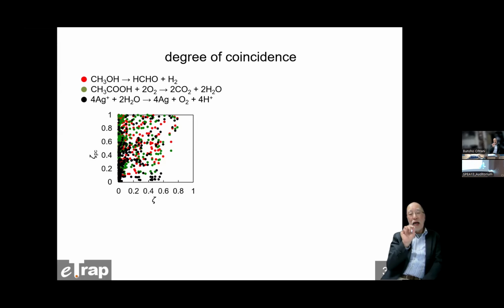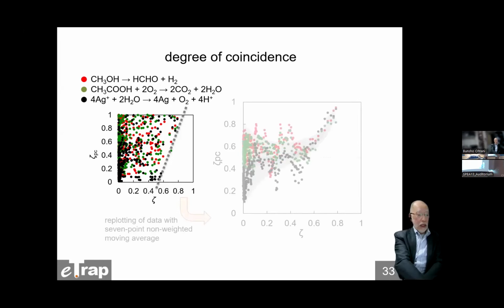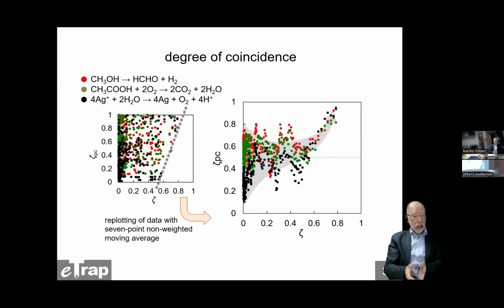This plot is of pairs of titanium oxide, and actually there is almost no relation between them. However, here is a line. This means the pairs with a higher degree of coincidence didn't give a large difference in photocatalytic activity. That means similar photocatalysts, titanium oxide, show similar photocatalytic activity. By taking the moving average, we can obtain this plot. So this plot says that if the zeta value is lower than 0.6, it is zigzag, accidentally high or accidentally low. But if the zeta value is higher than 0.6, it is increasing.